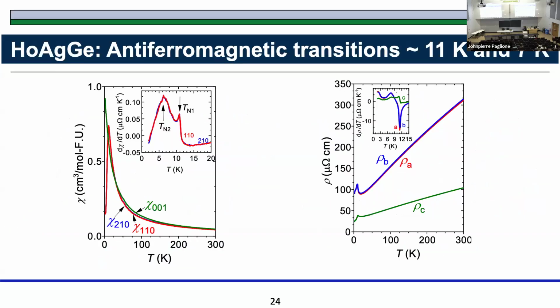And this particular compound that I will show you some data about is holmium silver germanium. It orders below about 11 Kelvin, and it has a second transition below 8 Kelvin or so. So there are two transitions. The interesting one is the lower one, so I'll basically focus on the lower one. This is the resistivity, showing similar transitions here.